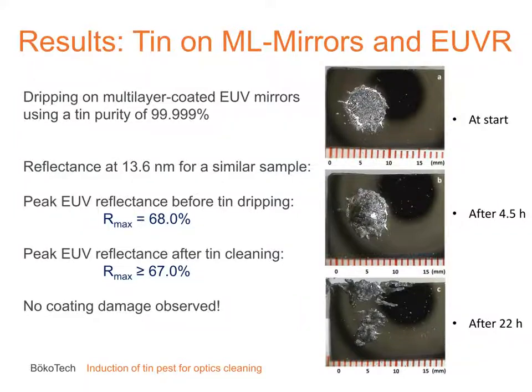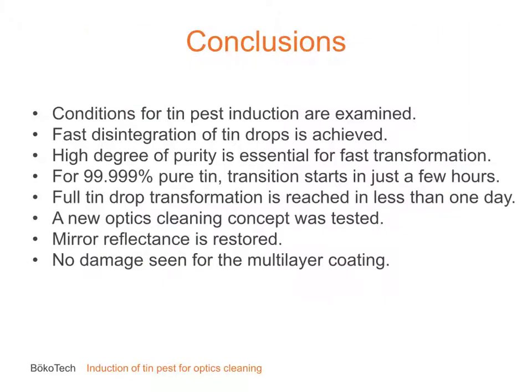This shows my observations for a tin drop on top of a multilayer coated mirror when using tin of 99.999% purity. The full transition occurred in less than 22 hours. For another mirror sample, the reflectance of EUV light at around 13.6 nanometer was measured before and after tin drop conversion. The initial peak reflectance of 68% was reduced after cleaning by no more than 1%. This shows that this cleaning method does not induce any significant damage in the mirror coating.